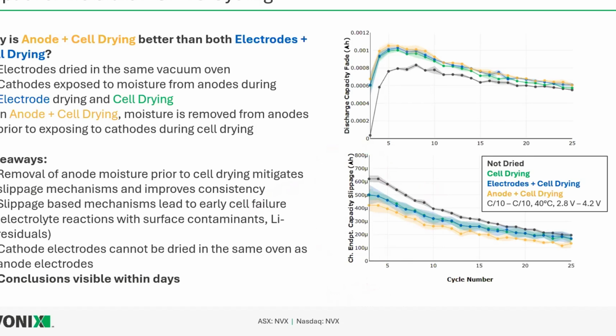If you're trying to look at the mechanisms that are driven by kinetics, you can definitely use UHPC at higher C rates. So in the last webinar, you can find it on Voltaiq's YouTube page, I looked at the effects of cell orientation on electrolyte pumping and how that would impact performance long term. And in those cases, we were actually testing cells at C/3 and 1 because we were looking for differences in slippage or in coulombic efficiency that would be driven by kinetics.